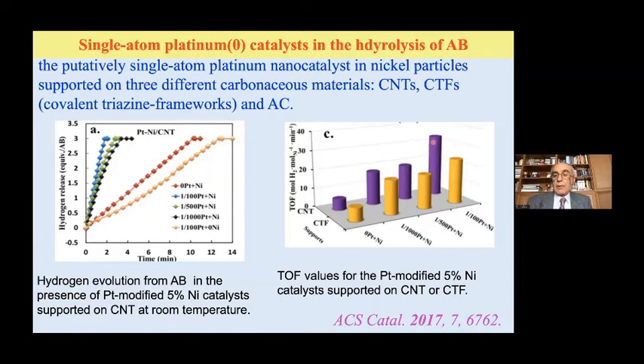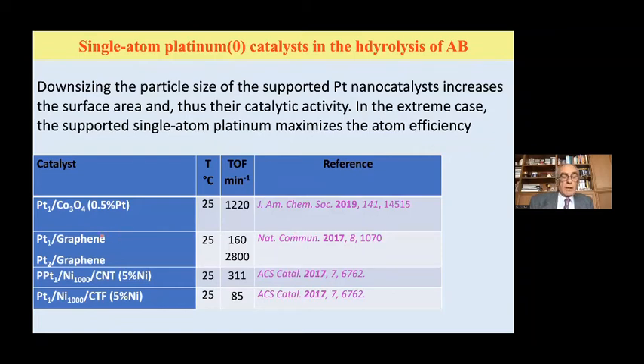That is important. However, we will see that the conclusion is not really correct, because when we talk about platinum in the nickel particles, that platinum cannot be considered as a single atom, because platinum is surrounded by the nickel atoms. Maybe we can consider it as an alloy in that case. So nickels are certainly interacting with the platinum. That means that platinum cannot be considered as a single atom, and therefore the activity should not be assigned to the platinum alone. It should be assigned to the whole nanoparticle, platinum plus nickel. And therefore, I don't want to discuss that one more.